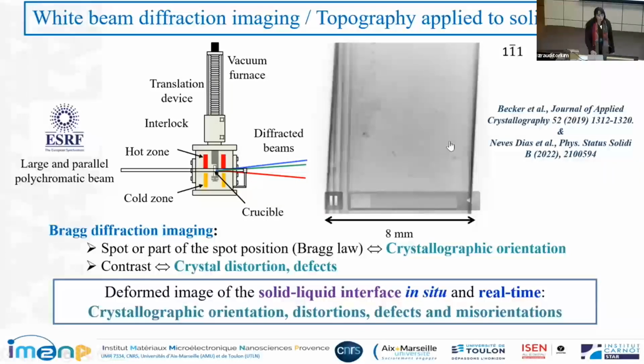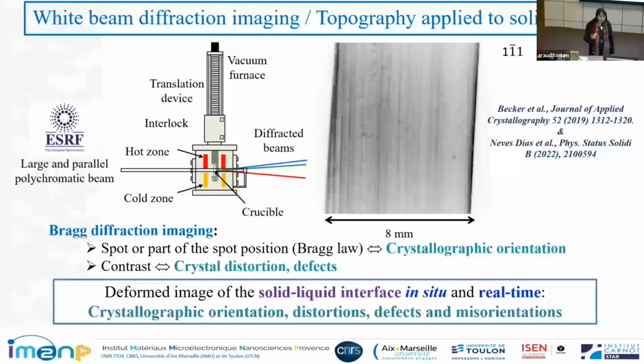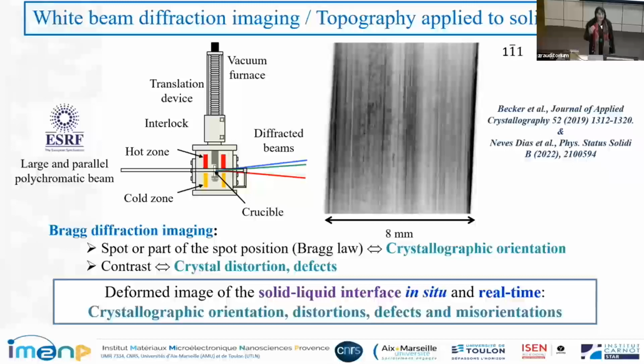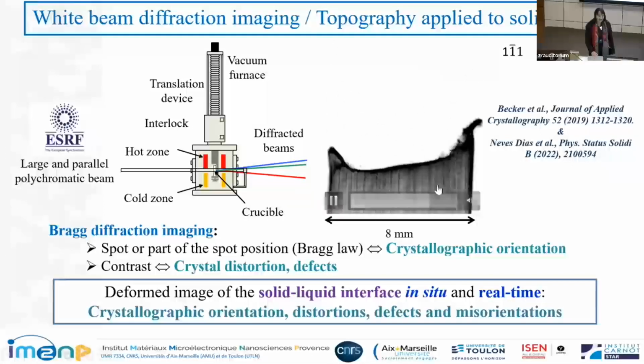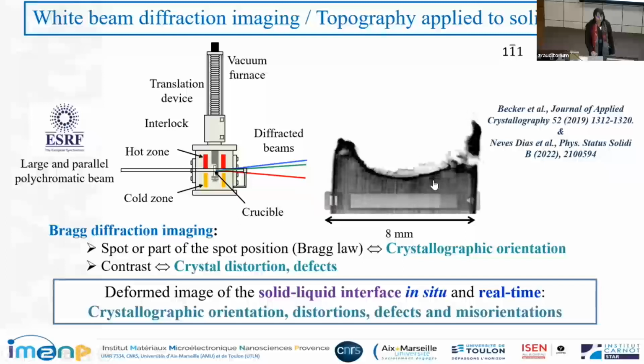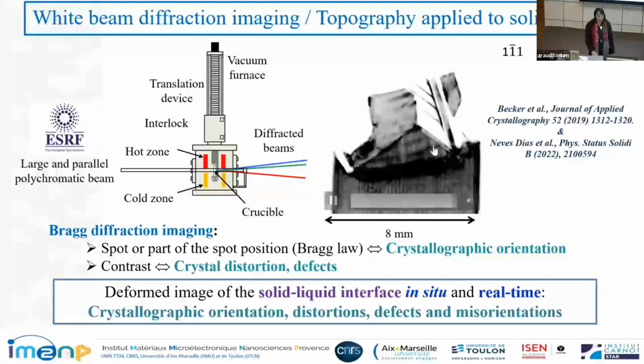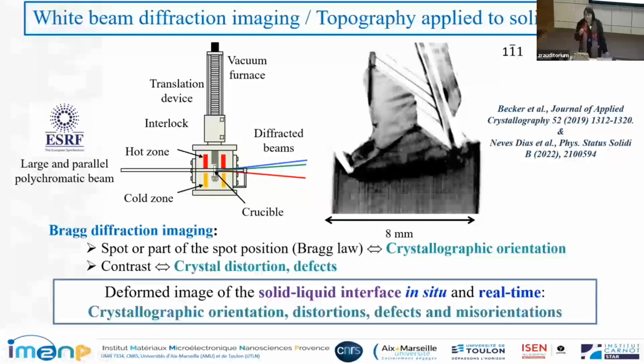What you see here is a monocrystalline seed. It's the topograph. You see the propagation of dislocation groups while we are heating the silicon seed. Then we will melt it partially and start solidification from this monocrystalline seed. And what we follow is the dynamics of the dislocations during all these phases, heating, solidification, and later on cooling down, the interaction of the different defects. And here, for example, you have the formation of the twin boundaries I've already mentioned. And we try to understand the interaction of all these defects.